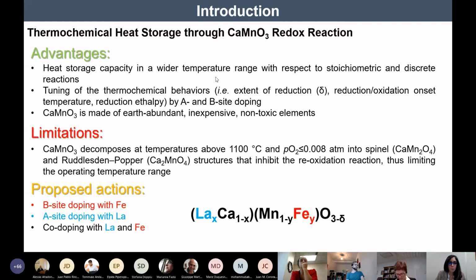However, these materials present a main limitation. It decomposes at temperatures above 1100 degrees C and for PO2 below 0.008 atmospheres. So this is going to limit the operating temperature range of the materials. In this study, we proposed several actions: B-site doping with iron, A-site doping with lanthanum, and also co-doping with iron and lanthanum.